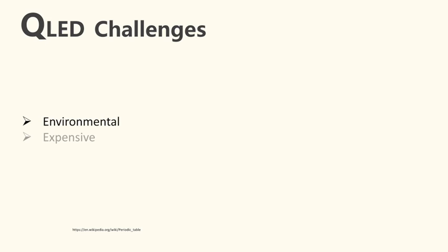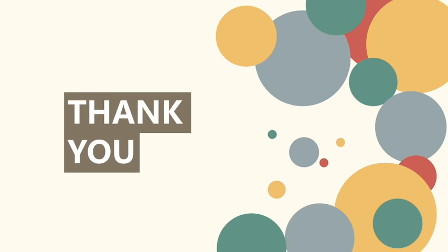Second, because the current fabrication process is not very mature, it is still very expensive to buy QD-based products. Thirdly, because the blue QD is much smaller than the red and green QDs, there are many problems with blue light QLEDs concerning their stability, quantum yield, and efficiency. Alright, hope this video can give you some idea about QLED, and thanks for listening.